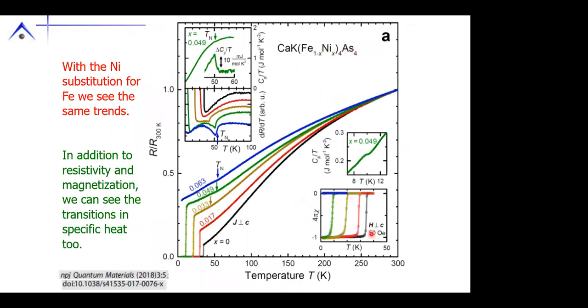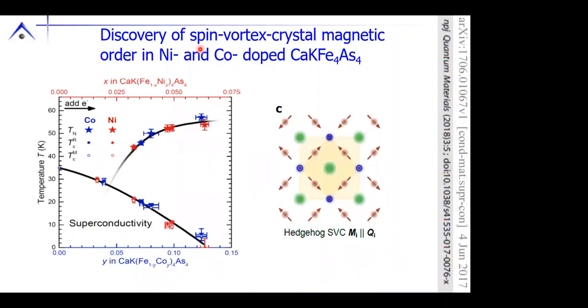As we titrate in nickel, we suppress the superconductivity in the magnetization, we suppress the superconductivity in the resistivity. Again, in the resistivity, we see this new feature come in and move up. We can see this new feature in specific heat as well. Now, if we take those data and plot them together, we see several things. First of all, the temperature doping phase diagram for cobalt and nickel is identical if you scale these by a factor of 2. This is very similar to what we saw in the barium iron 2 arsenic 2 materials, that electron count is key, okay?